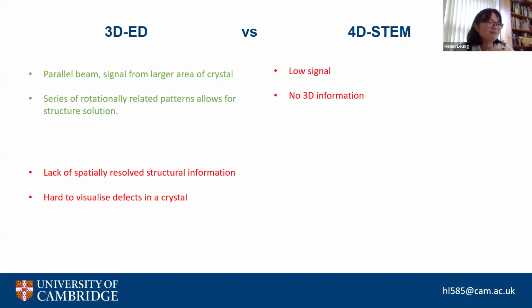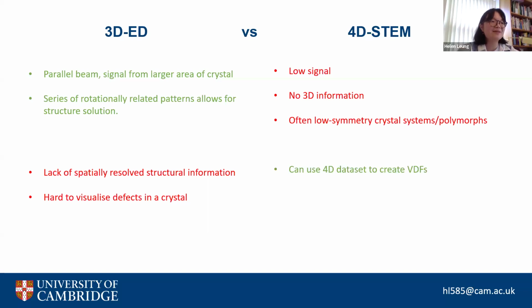Yeah, that's pretty true. And you often have very low symmetry crystal systems or polymorphs. So this just exacerbates the problem because you have many different orientations that could match, and you're working with very few Bragg spots. And the good side of it is that you can use your 4D dataset to create virtual dark field images, and you can really start to isolate signal from different parts of the crystal.